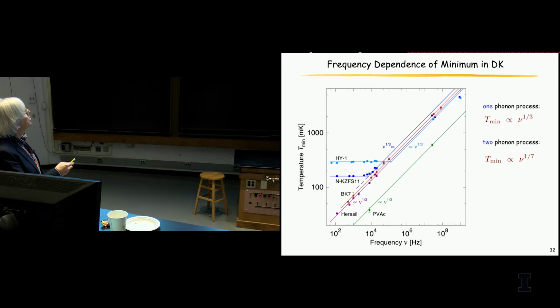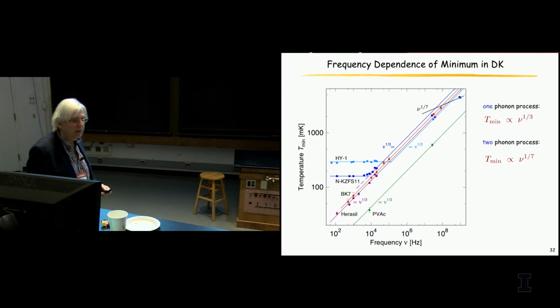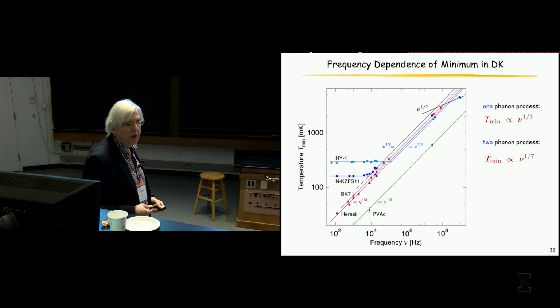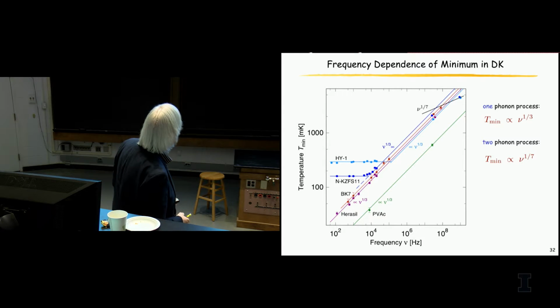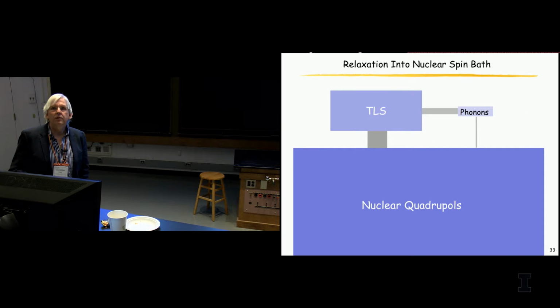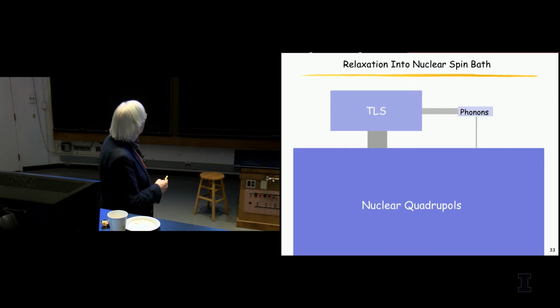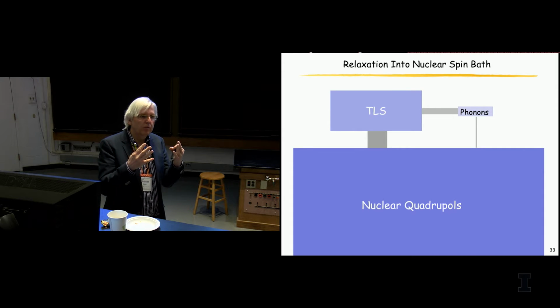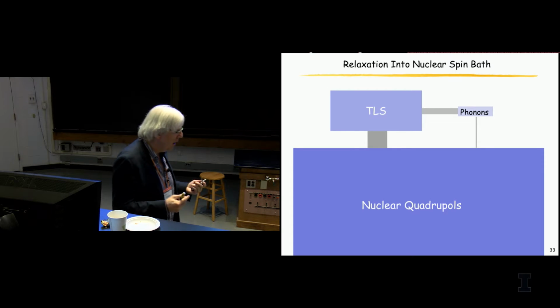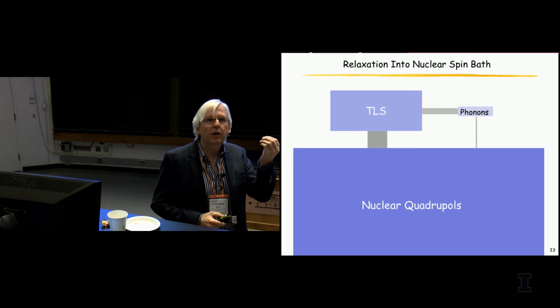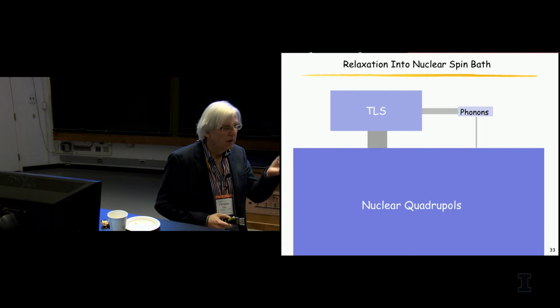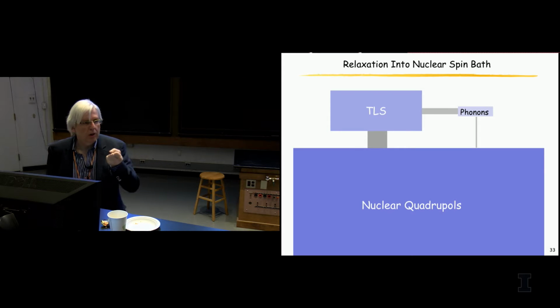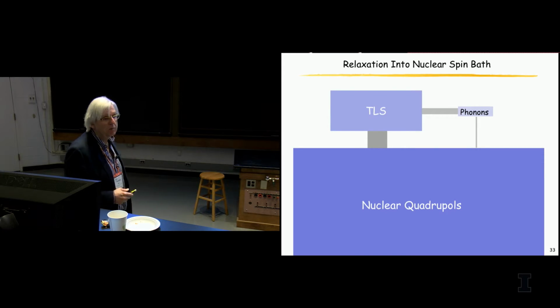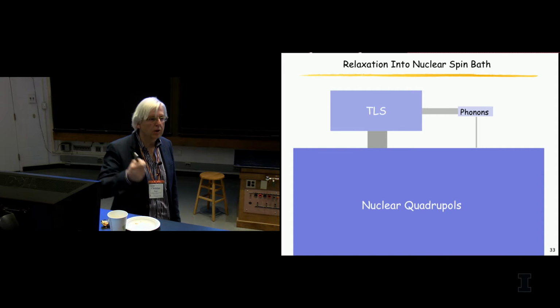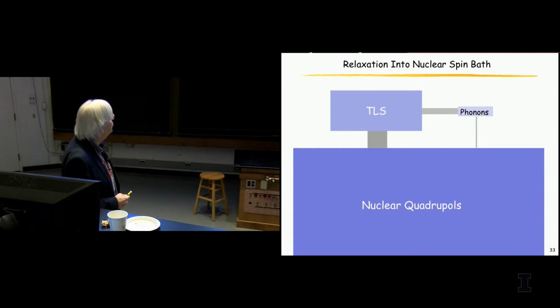You have the one phonon relaxation, and by the way, two phonon relaxation sort of is indicated up there. But something else is happening here. And the something else is a speculation I will give you of the following. We have the nuclear spins in those systems, the nuclear quadrupoles. Now, if you look at the specific heat they would produce, or how many degrees of freedom we have, in glasses, typically, the concentration of two-level systems is 10 to the minus 6. So 1/1,000,000th of an atom is involved in such a tunneling process. The number of phonons becomes very small at such low temperatures, but the nuclear, if you have 1% of holmium in such a glass, this is a huge heat capacity. And it's a huge bath.